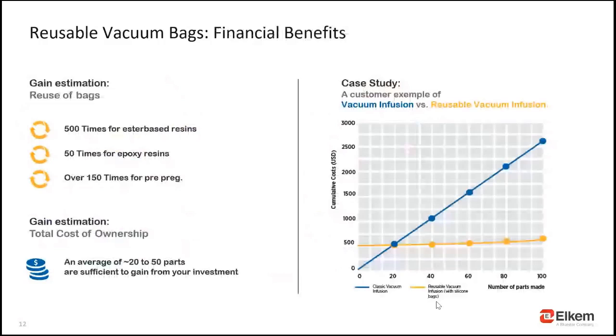RVB's cost reduction is directly dependent on the cycling life. From Elkem's experience in composite molding, different resins will have different impact on the RVB life, going from 50 cycles without any mold deterioration for more aggressive resins, up to 500 cycles for general resins. From an economic point of view, RVBs have a payback turnover around 20 cycles. In other words, composite goods with more than 20 molding cycles are suitable and economically more viable when RVB infusion is chosen.